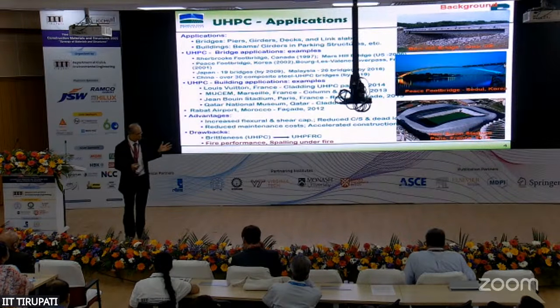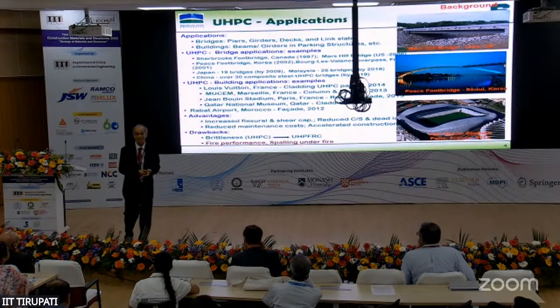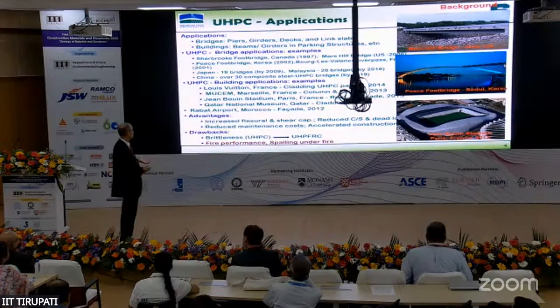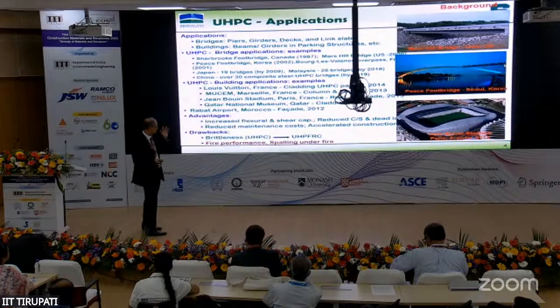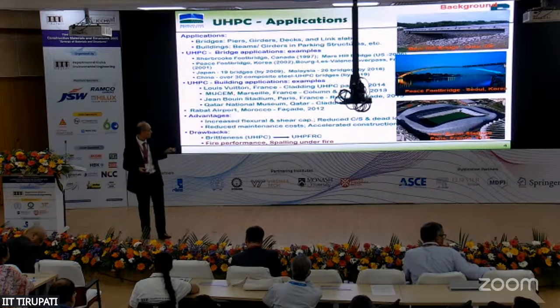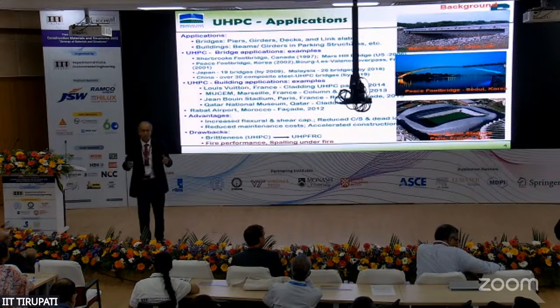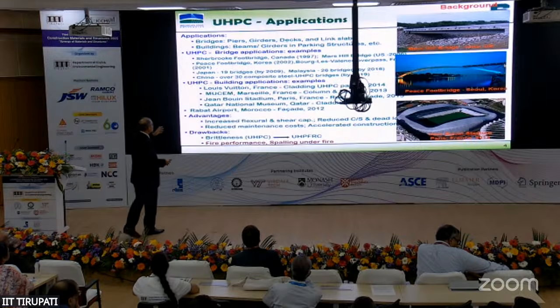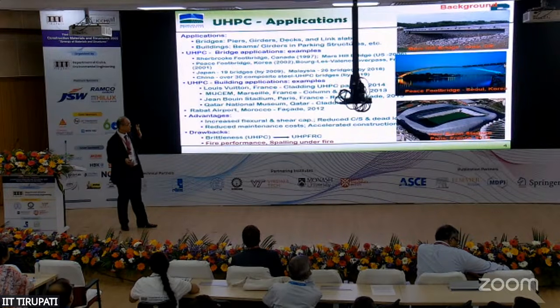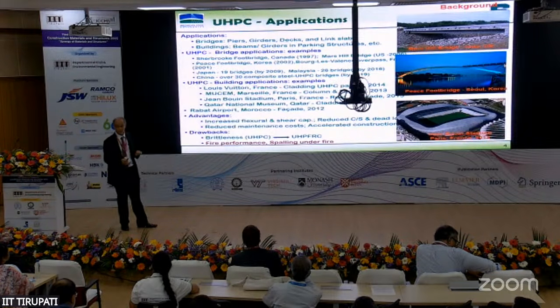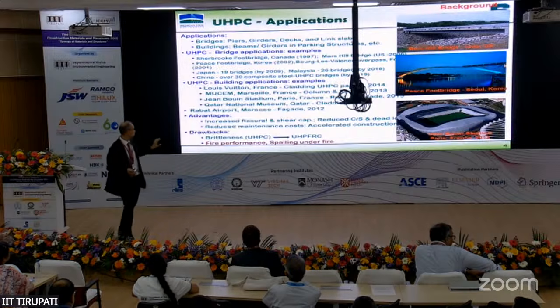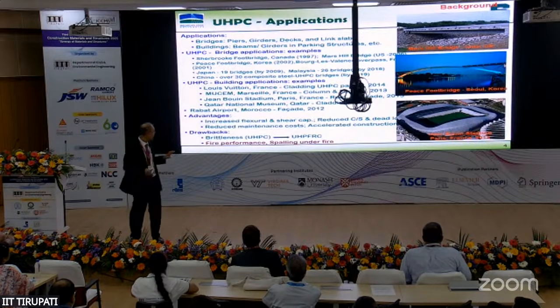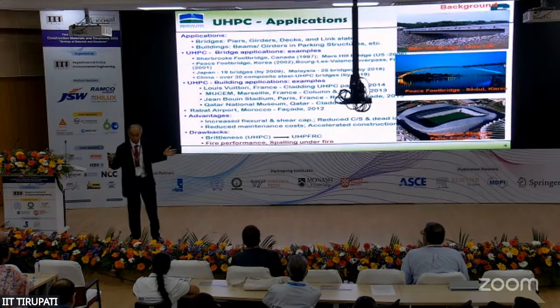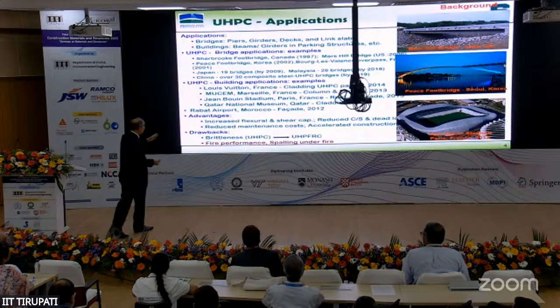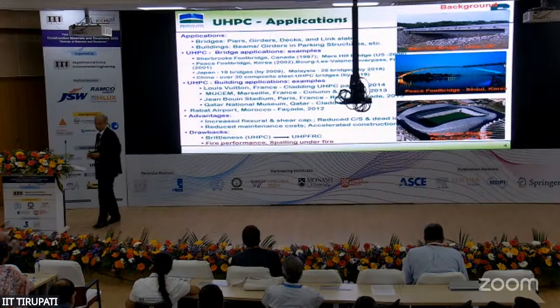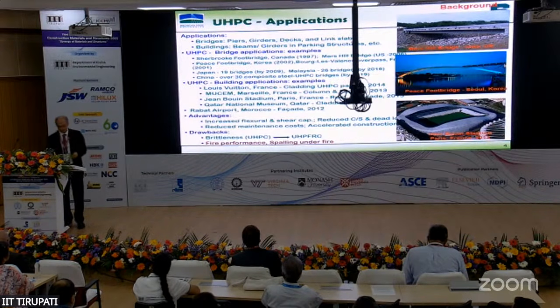Now, structurally, when you use this material, you have a lot of advantages. High flexural capacity, increased shear capacity, cross section will be much less, and even maintenance costs will be less because no corrosion and other issues. But when it comes to problems, brittleness you can overcome with UHPC fibers. Another problem can be fire, and fire is very important.